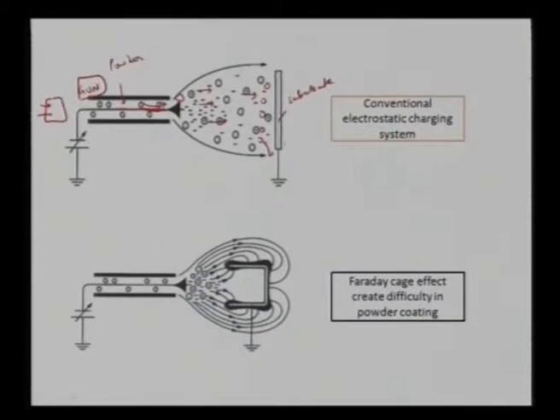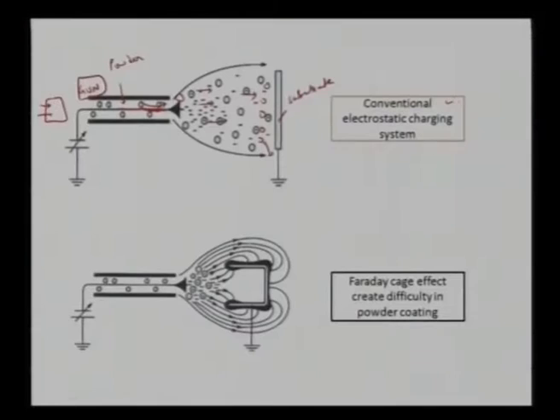But in this process, all the powder particles have similar charges. So there is some sort of electrostatic repulsion, and that electrostatic repulsion is the cause of uniform dispersion of the powder particles. So that's what happens in the conventional electrostatic charging system.